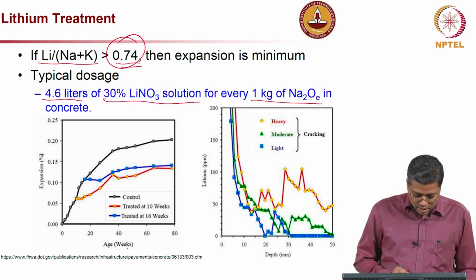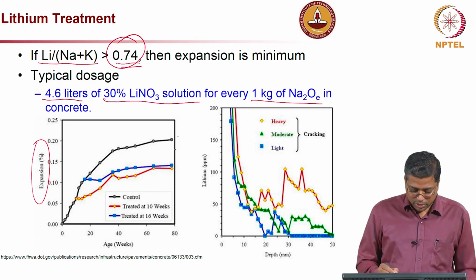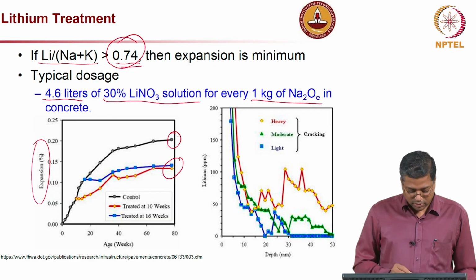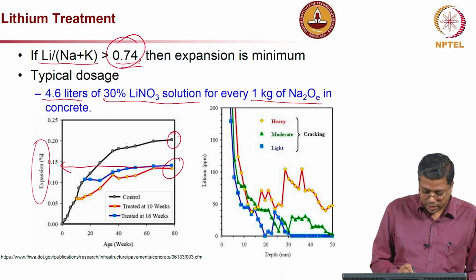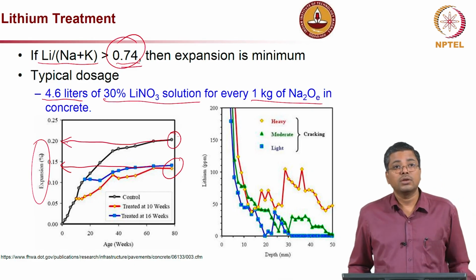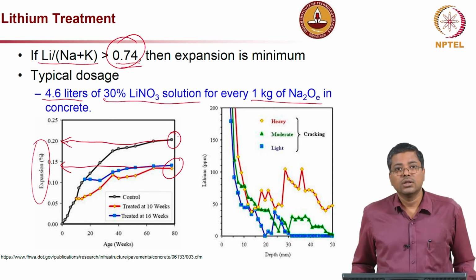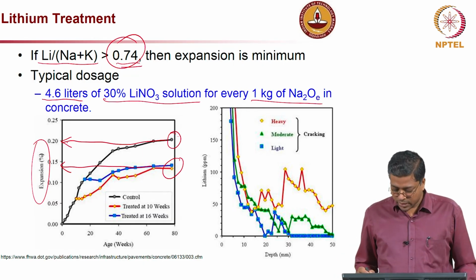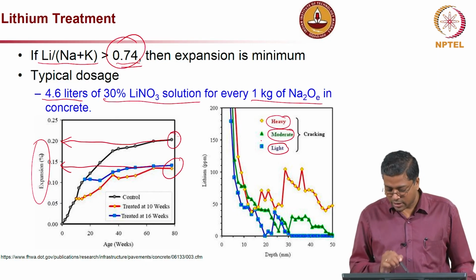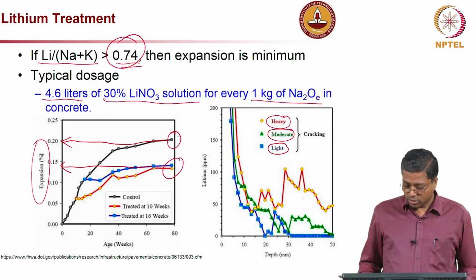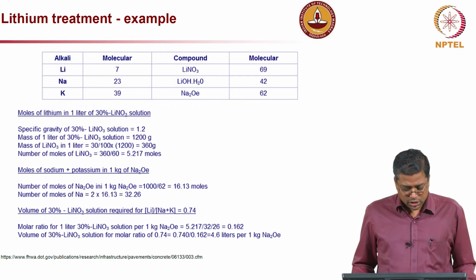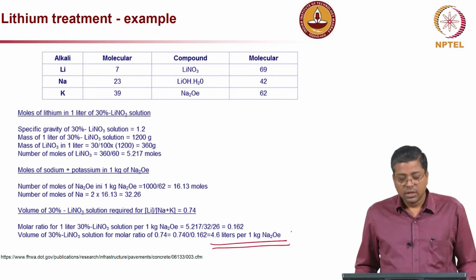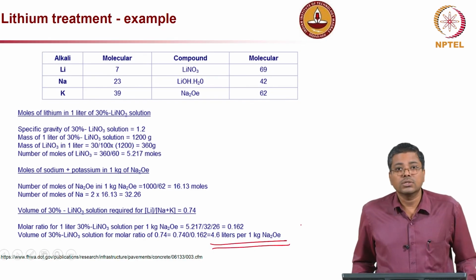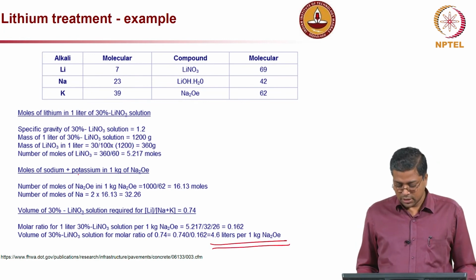The graph here at the bottom left shows the difference between the expansion exhibited by a control system, that means no lithium treatment, and lithium treatment for 10 weeks and 16 weeks. So, the point is you have a significant reduction in the expansion from about 0.2 to less than 0.15%. That is about a 30% reduction in the expansion. And if you have heavy cracking, moderate cracking or light cracking, the amount of lithium requirement is also apportioned accordingly. This is an example showing how the 4.6 liters per kg sodium oxide equivalent is come up with. You can go through this in more detail later, and so I think that is it.